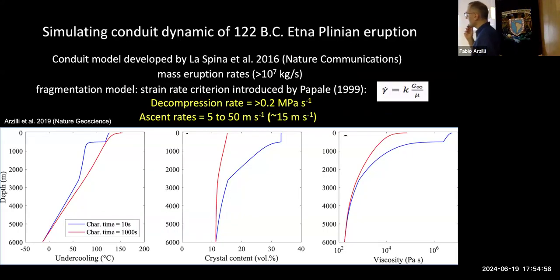So we put all this kinetics data into a model that we developed in 2016, where we can simulate basaltic magma ascent within the conduit, considering the strain rate criterion introduced by Papale in 1999 for magma fragmentation. We simulated the conduit dynamics of the 122 BC Etna eruption, considering two characteristic times, which means that we have two kinetics. One is fast, one is slow. Here with the blue line, crystallization is really fast, considering our experiments. It means that equilibrium is reached quite fast. Instead, for the red line, we used a very slow crystallization kinetics that simulates a very slow approach to equilibrium.